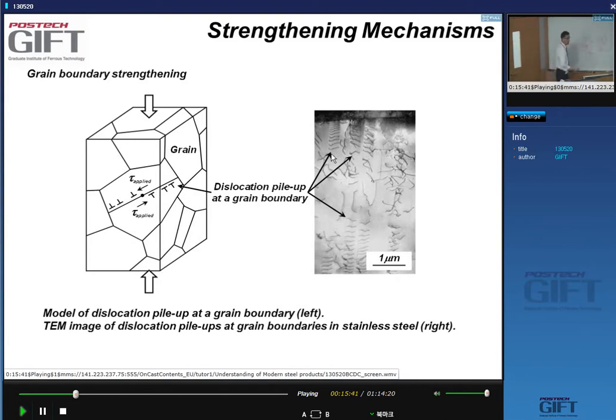If the grain boundary was not there, the dislocation loop would expand until the dislocation would exit the crystal. In this case, they can't do this. They're just stuck at the grain boundary. So in order to create plastic deformation, I have to constantly increase the externally applied stress to push these dislocations closer and closer to the grain boundary.